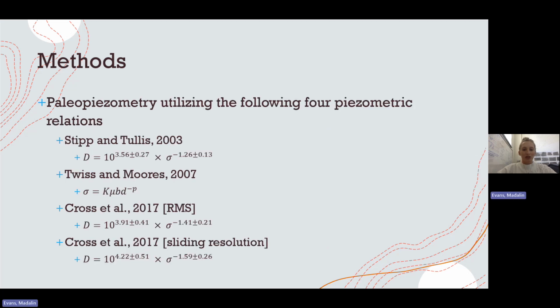These are the piezometric equations that were used to help find paleostress. Trends from previous works, as well as the experimental computations, were then compared to a theoretical piezometer by Twiss 1977. The following exponents here derive from the recrystallized grain slopes per individual study. Stipp and Tullis 2003 have an equation where D represents the recrystallized grain diameter and sigma is stress. Twiss and Moores have an equation where sigma is also stress.